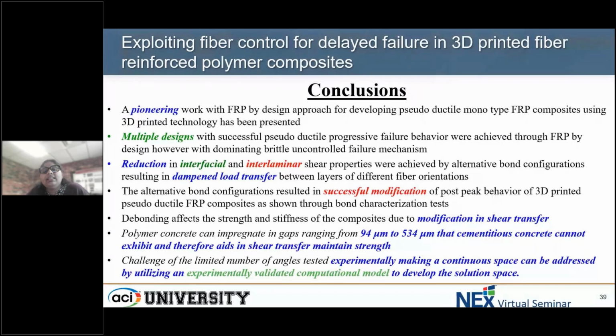But to think in the materials aspect also, that strength and stiffness can increase if the filament itself improves in terms of just the material. If you look at concretes, polymer concrete can impregnate in gaps ranging from 94 to 534 micron, which cementitious cannot impregnate, and therefore that could aid the shear transfer mechanism also in terms of the multiple fibers interacting with each other.